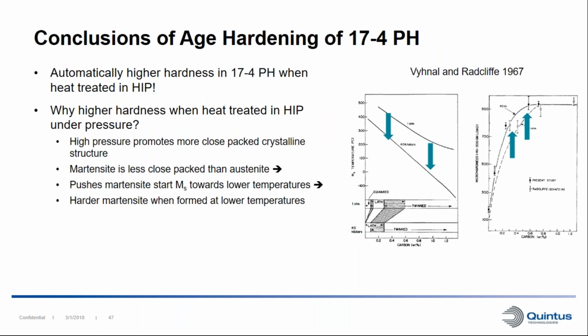So this means that you would automatically get a material with higher hardness when you perform the age hardening in the HIP for 17-4 PH. The theory of why we have this higher hardness in the martensite, or in the final microstructure, when we do it under pressure is that high pressure promotes the more close-packed crystalline structure, and martensite is less close-packed than austenite. This will push the martensite start temperature to lower temperatures, and when you form martensite at a lower temperature, it will be harder.